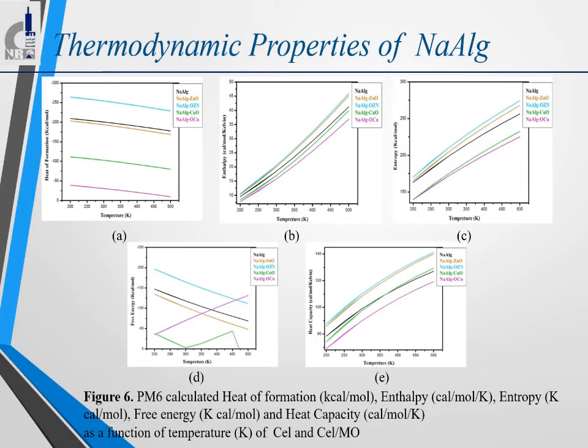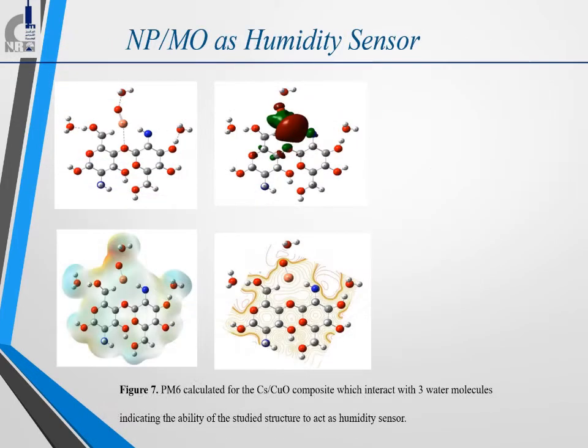While for the sodium alginate group, the interaction of sodium alginate with metal oxide recorded unstable behavior with increasing temperature. So from all thermodynamic properties of all groups, we can conclude that the most enhanced and thermally stable structure was chitosan copper oxide. So we chose chitosan copper oxide to be applied as a humidity sensor.